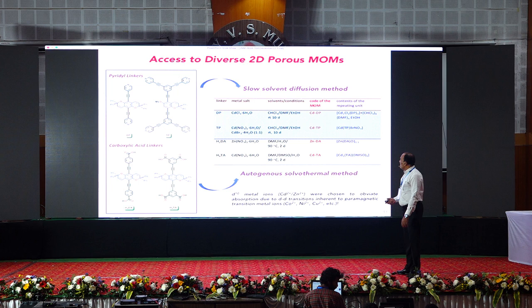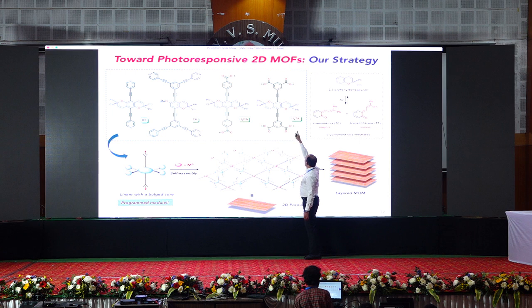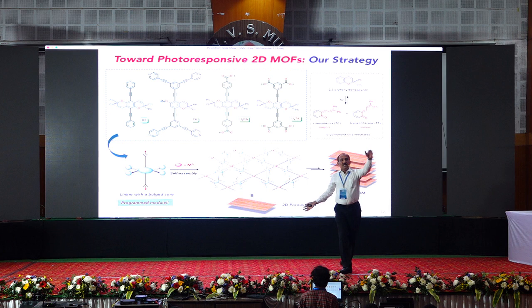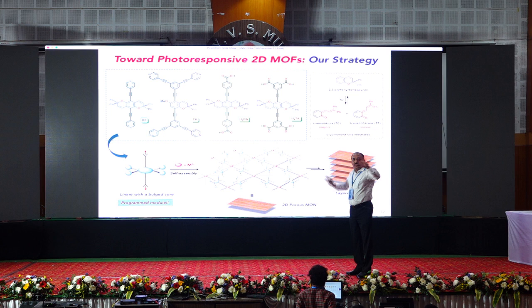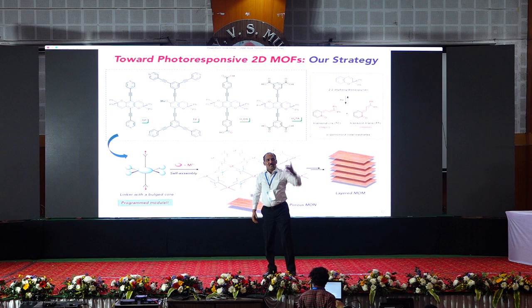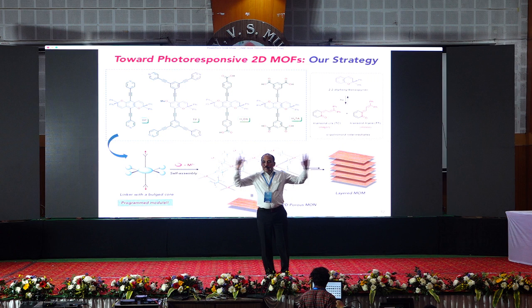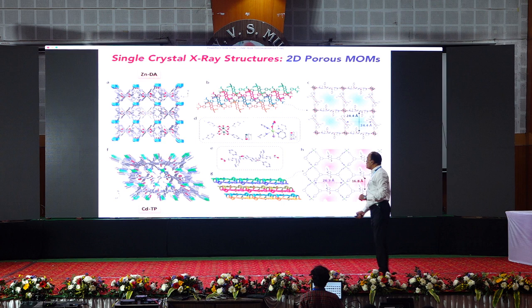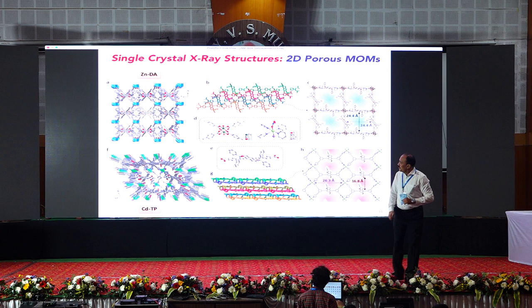Because if you look at this particular carbon here, you have one phenyl ring coming towards you, one phenyl ring going towards the board, the screen. So you have a material like this with phenyl rings in a flat system sticking backside and front side. Now you put metal, the metal assembles only in this direction because for another molecule to come in this direction, there is a hindrance, it's a blockade. So you basically dictate the molecule to assemble only in two dimensions, which is exactly what you see in the crystal structures everywhere. Even if you want to get to a three-dimensional structure, you don't get it because of the hindrance that is built. So a variety of materials, not just one.